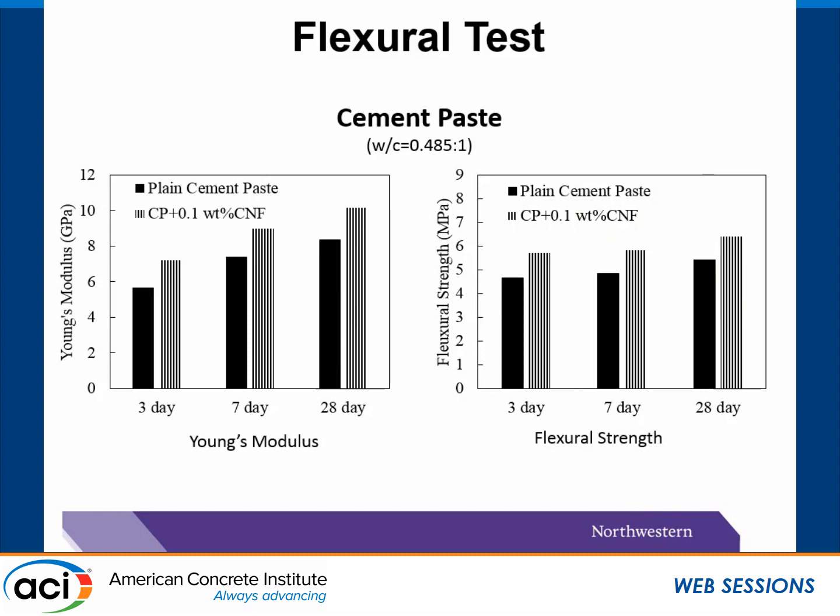The CNF is first added in cement paste, and the beams are tested under flexural test. We have seen 0.1% of CNF addition increase the Young's modulus from around 8 to 10 gigapascal at 28 days. The flexural strength increased from 5.4 to 6.1 megapascal at 28 days of age.